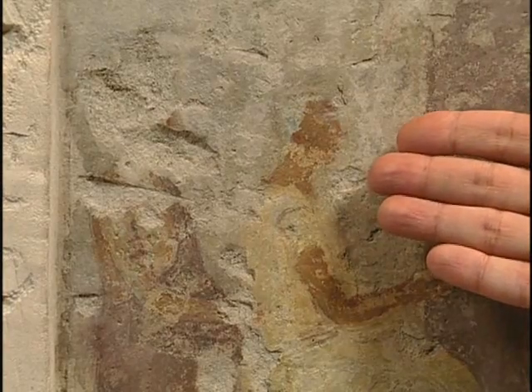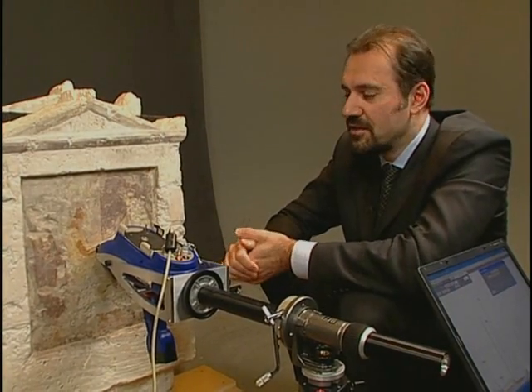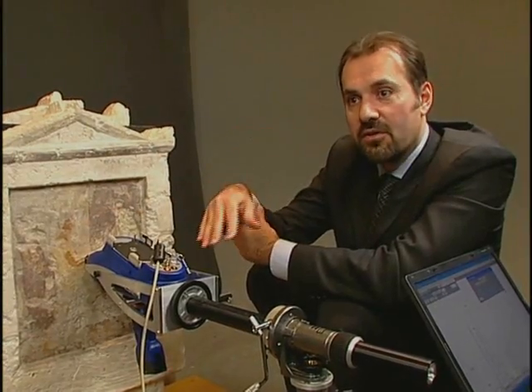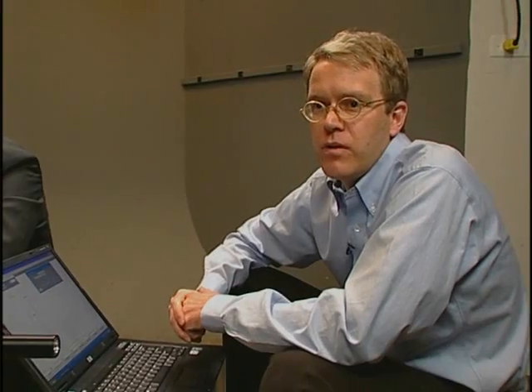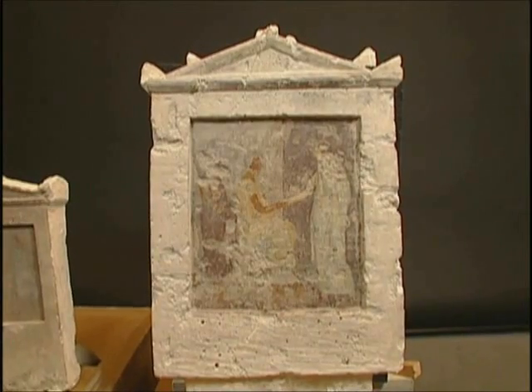It's a restricted palette — resources used wisely. We have yellows that are based on orpiment, an arsenic compound known since antiquity. These browns are ochres, so earth colors. And the use of blue — probably Egyptian blue, which was a synthetic pigment discovered by the Egyptians. We see it probably here as an underpaint on the hair of the man; the actual paint layer representing the hair is lost, but we see this underpaint which probably had the purpose of brightening the color. These sorts of studies are really letting us put the color back into antiquity. We've inherited a lot of aesthetics since the Renaissance about how antiquity is monochromatic, essentially about the marble substrate. As these detailed technical studies are made, we can accurately reconstruct what the visual aesthetics and visual culture was of antiquity.